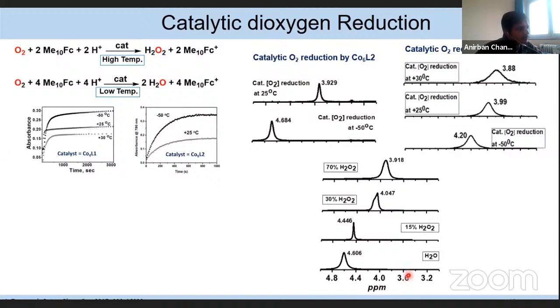So in this NMR spectra that I am showing, it is a control spectrum. In the same reaction condition, in deuterated acetone in presence of acid, decamethyl ferrocene, and in presence of my catalyst using oxygen, if it's pure water in absence of any hydrogen peroxide, I got a signal at 4.60 ppm. And when I increase the amount of hydrogen peroxide, then I see the signal is shifted from 4.6